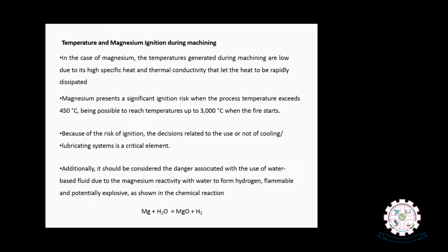However, if you are using coolants, we should select one that is free from water. Because of the risk of ignition, the decision of whether or not to use a cooling lubricant system is critical. Additionally, the danger associated with water-based fluid should be considered, due to magnesium's reactivity with water to form hydrogen, which is flammable and potentially explosive, as shown in this equation. Therefore, it is suggested not to use water-based coolants. Dry machining of magnesium can be conveniently done. If you would like to use coolant, it is suggested to use water-free coolants.